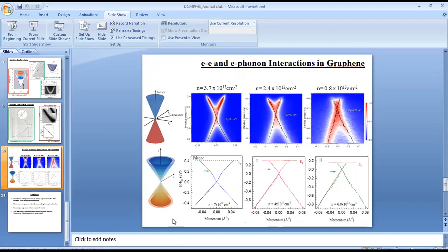Energy resolution typically is 10 meV, you can say. People quote it as 5 meV, in some cases 1 meV, 2 meV. But in those cases, you have to adjust the experimental setup in such a way that your experiment time goes up very high. As I said, you cannot perform these experiments for a very long time because the oxygen, nitrogen, whatever residual gases in the chamber will deposit on it. So you cannot do it. But the resolution can be achieved up to 1 meV.